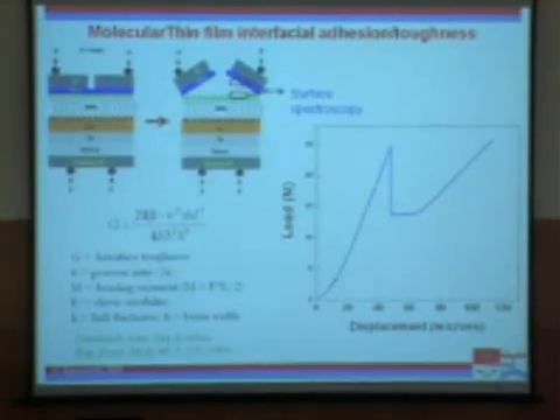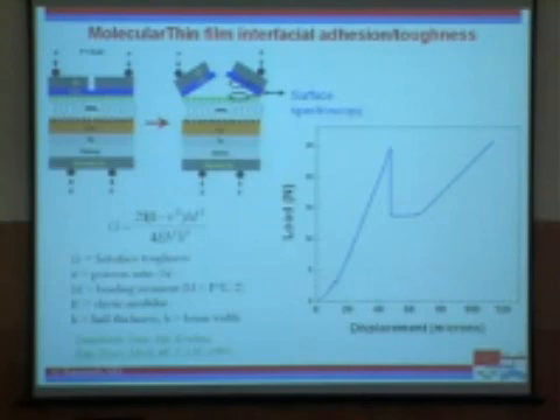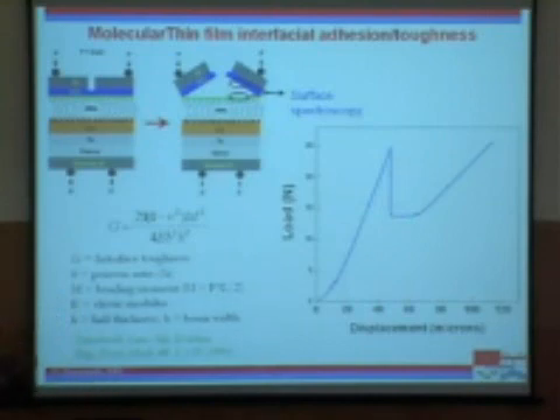We also have a technique which is very powerful to measure the interfacial adhesion or toughness quantitatively. The way we do this is we create a test structure like this. It's a 4-point bending test structure, and we create a notch. Once you bend it, from the notch tip you have a crack going through, and it'll go down to the interface, the weakest interface, and grow laterally, which gives rise to a load versus displacement curve that looks something like this. And this plateau corresponds to the crack going through the weakest interface. From that you can get the toughness value quantitatively.